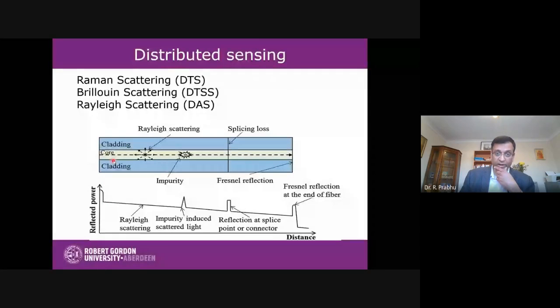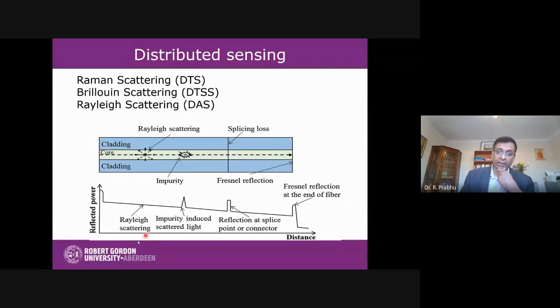So you can see the long optical fiber. As the light propagates from one end to the other, based on impurities or non-uniformities in the fiber, there will be a reflected spectrum in the time domain, backscattered light. That can be correlated to distance if the refractive index of the core is known. You can see the continuously decreasing Rayleigh scattering, mainly due to the loss of the fiber, and impurities resulting in small peaks like this, and reflection due to splicing. OTDR, optical time domain reflectometers, can be used for monitoring the backscattered light and predicting what is happening along the fiber. So these are the basic principles that can be used for distributed sensing using optical fiber.